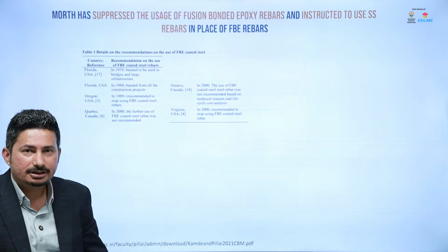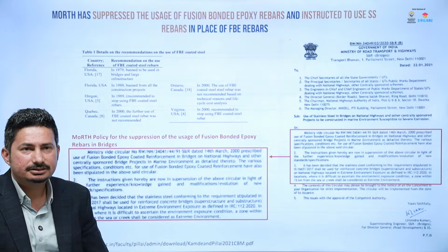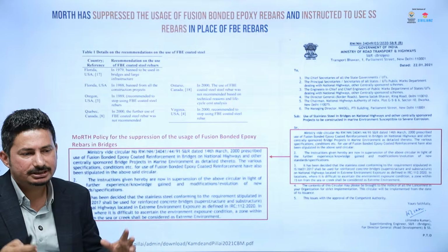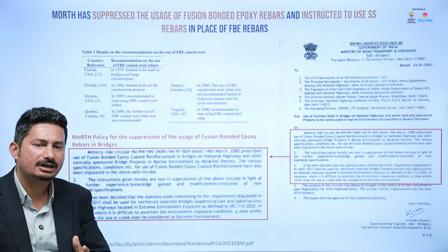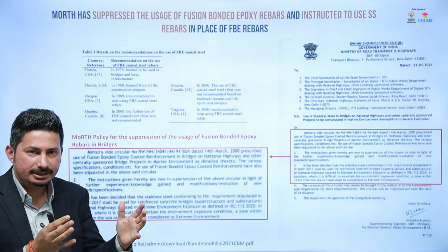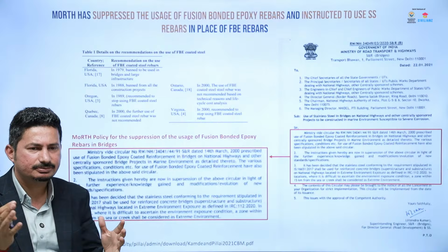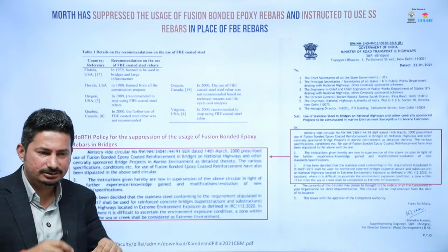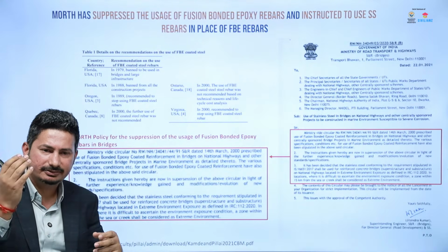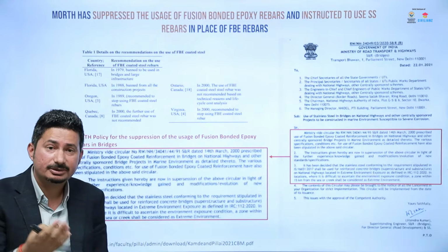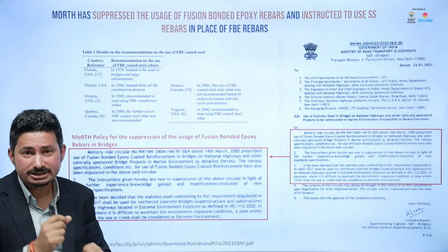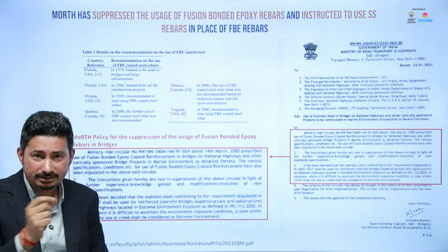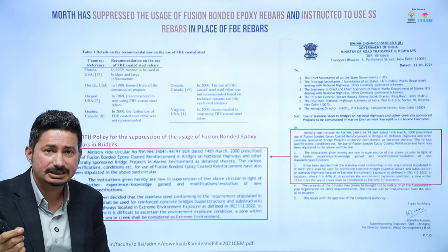Then talking about various countries, they are already moving away from epoxy coated rebars for certain applications, primarily because of these reasons. The coating breaks at site. Then we also have to increase the material requirement because the bond strength will not be as per TMT or as per stainless steel rebars.